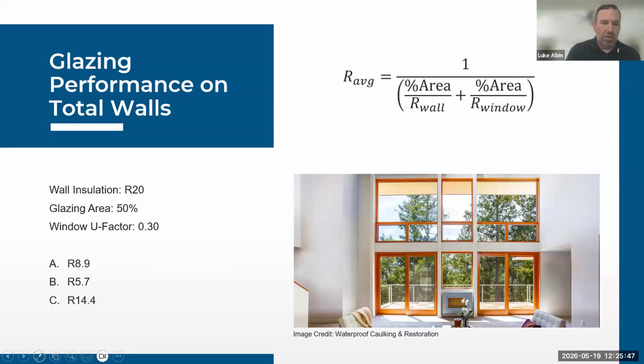So this is the only question here that we have in this presentation. But if we take this example, if we have an R20 wall, 50% glazing area, and a window U-factor of 0.3, which again, if you think about it, it's an R3.3 window. What would that overall assembly of the wall be when you take in this equation here that you see? Well, we find that with the R20 wall and an R3.3 window, the window has dragged this entire assembly down to an R5.7. So pretty significant difference there.